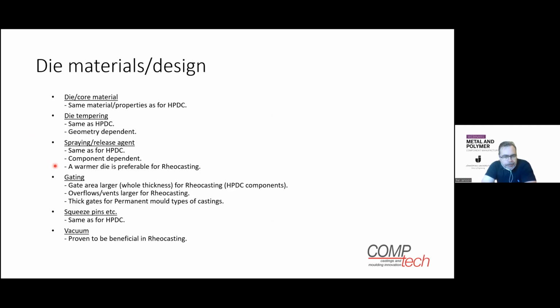The big change in the die is the gating and the casting systems. We are using larger, thicker gates. We prefer one flow so we can avoid metal meetings inside the cavity as long as possible. We also need larger overflows and vents, and especially thicker ones. It's very common that we need overflows where we have, for instance, a core behind which the metal meets. We place an overflow there so we can get out the metal that has met.